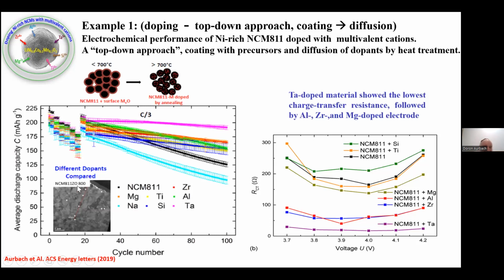By line scanning, by cross-sectioning, we can analyze and realize that we have foreign elements, so the doping is successful. I should say that doping also affects the surface. Since the final process is heating, we have segregation, and so doping also strengthens the surface very much. We have changes on the surface which are important.